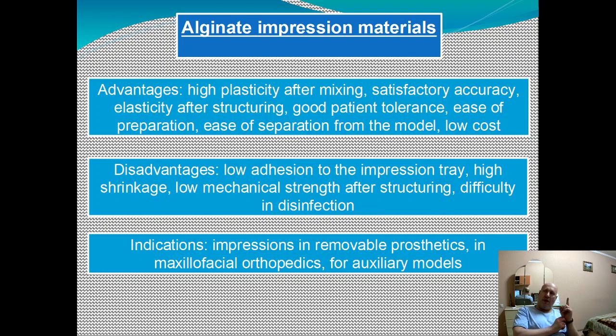So, due to high shrinkage, you have to cast the model from this impression from 15 minutes to 2 hours, not more. But also, for example, Hydrogum 5, they announced that we can cast model from this impression up to 2 days, if you put it into warm water. Indications: these impressions in removable prosthetics, in maxillofacial orthopedics, and for auxiliary models.